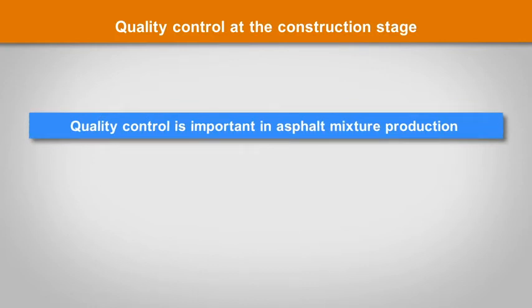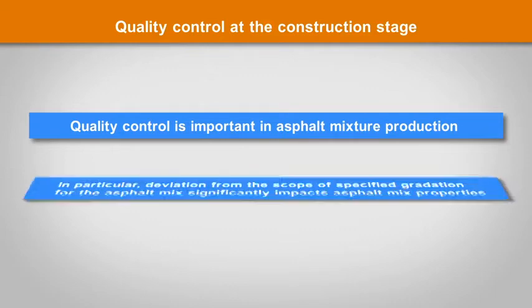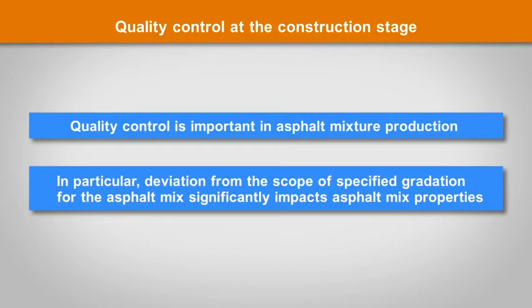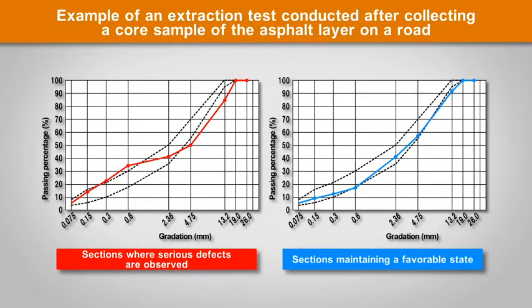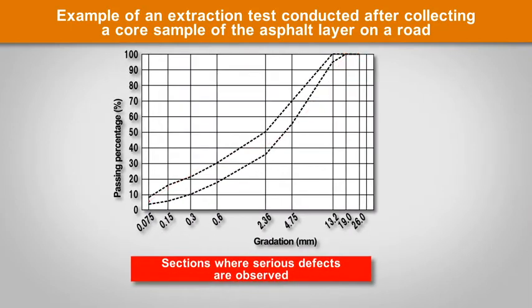When the paving works commence, quality control is important in asphalt mixture production. In particular, deviation from the specified particle size range of a specified gradation for the asphalt mix significantly impacts asphalt mix properties. This is an example of an extraction test conducted after collecting a core sample of the asphalt layer on a road. In sections where serious defects are observed, the test results show that nearly all gradations deviate greatly from the standard.